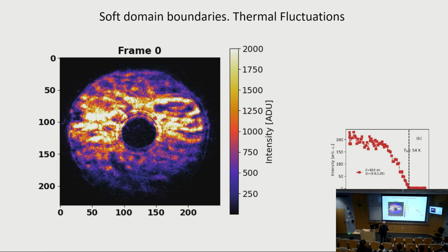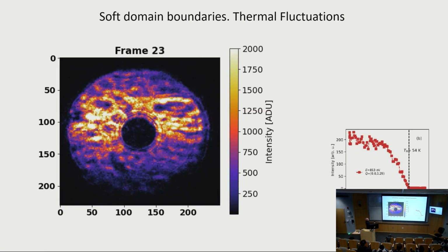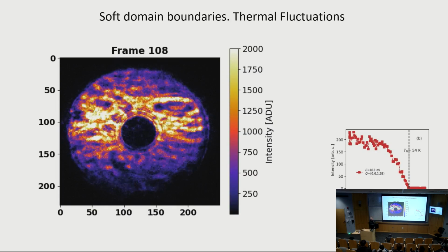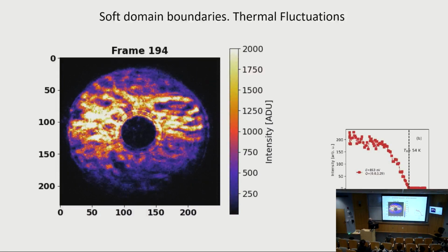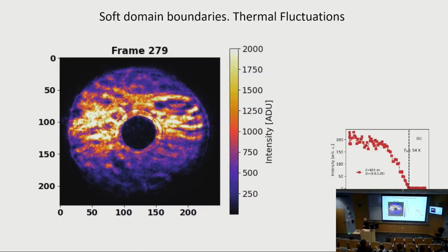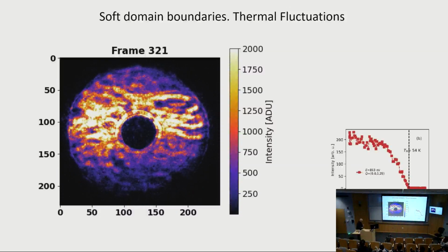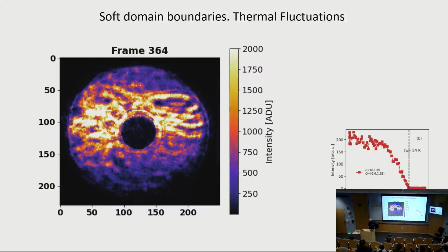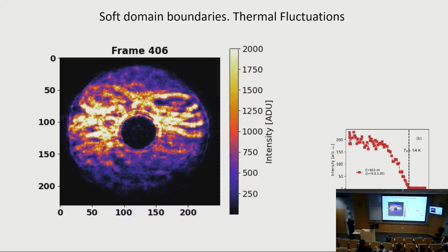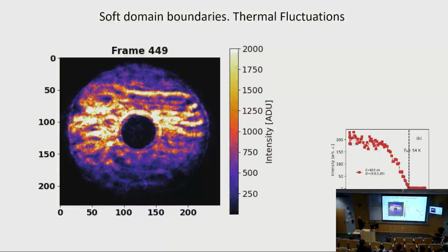So what it means is that it takes very little external perturbation in order to modify the antiferromagnetic domain pattern of this material. The domain boundaries are very soft and they can be moved by external probes. Of course, if you go close enough to the transition temperature, like 1 degree below the transition temperature, things start fluctuating, and you see this loop, this eye, closing and opening, right? Like a blinking eye here. So this topological defect, this loop, appears and disappears. These are thermal fluctuations near the transition temperature. At some point, this loop will collapse. It will have enough thermal shaking. So there is a lot of data for the data analysis, right? And as I said, these are actually unpublished data, so we're still working on it. The loop collapsed, right?